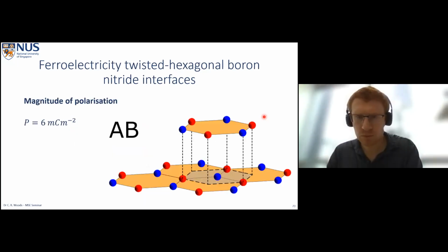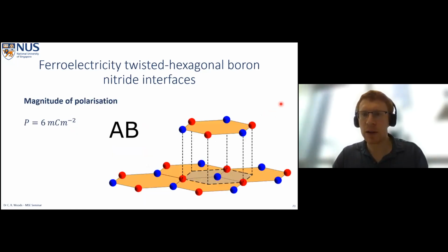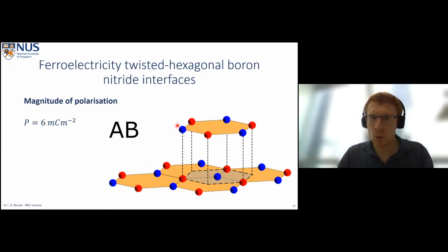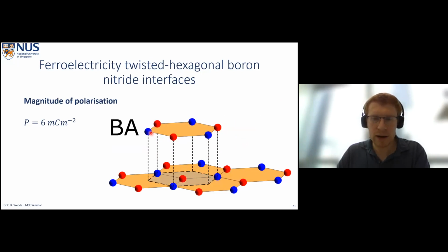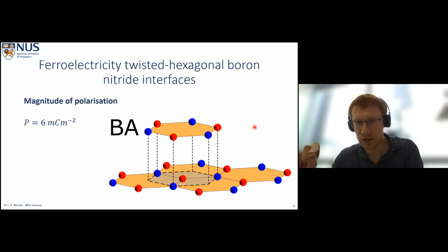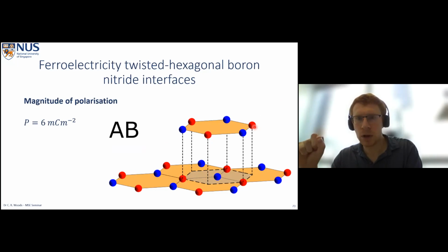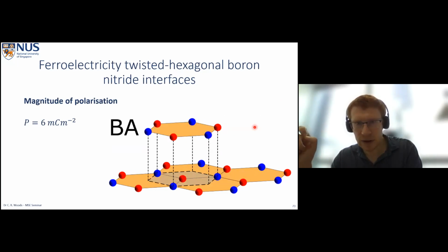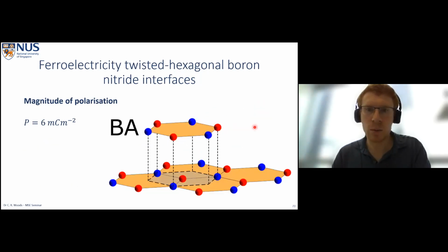And this corresponds to reversing the sign of our polarization in our AB or BA domains, so switching from AB to BA. We can understand this simply by looking at what I said before. So if we have AB, where we have boron on top of nitrogen, and then the nitrogen over the vacancy in the lower layer, all I have to do is translate this up by 1 atomic bond length, and I get to the BA system. So we can just go backwards and forwards between these, and all it requires is a small translation between two equally energetically favorable stacking configurations, and we can switch the polarization. So this is what we can observe, and this is how we get to ferroelectricity across our domains.